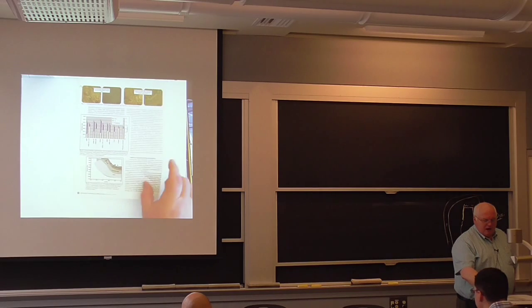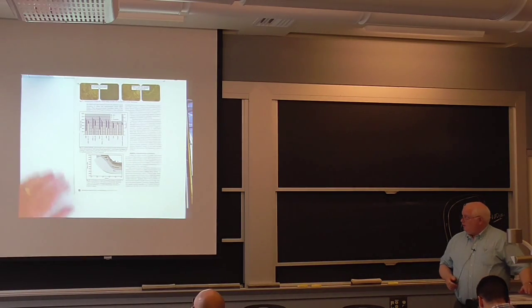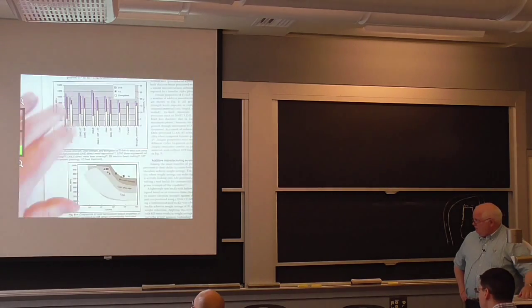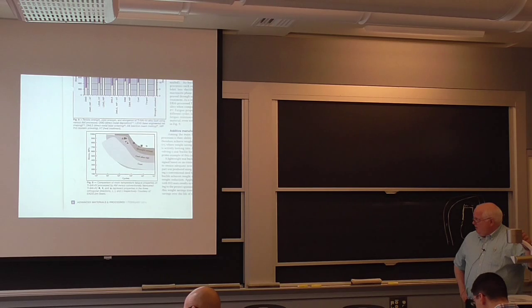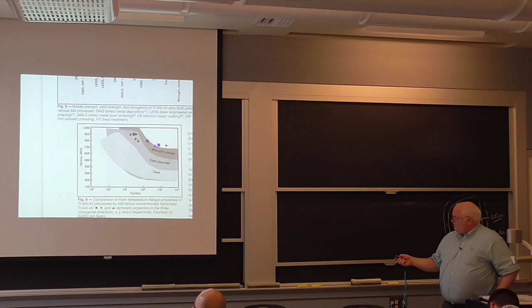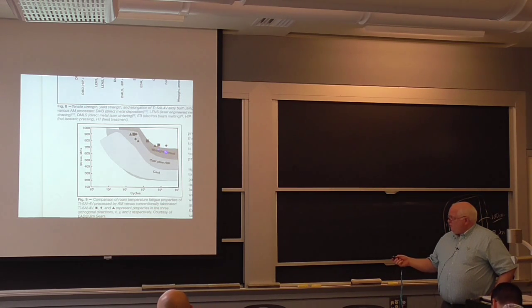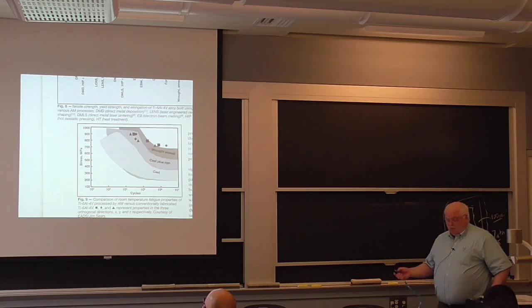Okay. We talked a little bit about HIPping yesterday at the end. And this is something I had in the notebook. This is actually on titanium alloys. It shows the fatigue strength of wrought, which basically means forged titanium, which is pretty pricey, cast plus hot isostatic pressing, or cast. Now they overlap quite a bit, but nonetheless, the hot isostatic pressing can get rid of any voids that are in the material and squeeze them out without changing the shape of the product. So you can think of it as forging without shape change.